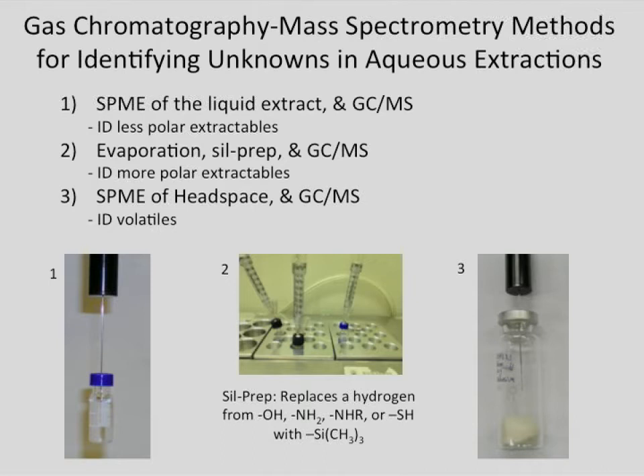We only had this as an option. We could have used vacuum, but it would have taken a little too long, I think. So what we did is just blew compressed air over the top of the samples and heated them to 70 degrees at the same time to drive the water off. We're likely driving off any of the volatiles that are there, but we know that sugars aren't very volatile, so we think those would be left behind.